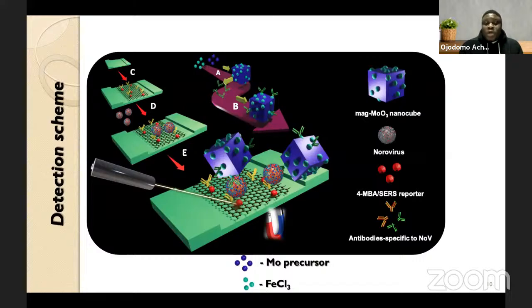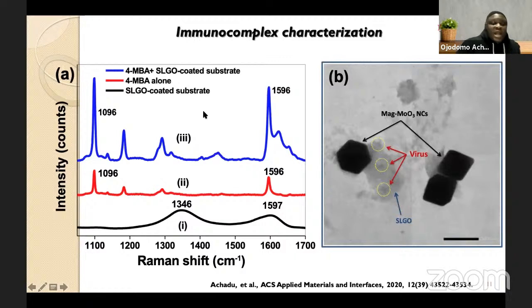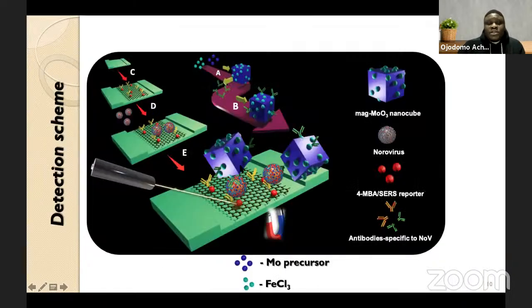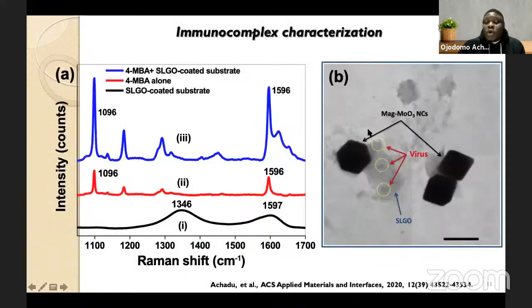So this is based on the immunocomplex characterization, whereby from the formation of this complex, we're able to confirm that yes, we can form it in solution, as well as on the solid 2D graphene functionalized platform. We're able to generate some TEM images whereby we can see some of the graphene nanosheet, not very clear, but we have a little bit of visualization of the virus. The virus is not very obvious based on size consideration. We have nanosheets of graphene of about 2 microns or thereabouts, which are much bigger. The virus size is around 30 nanometers relative to the nanocubes.